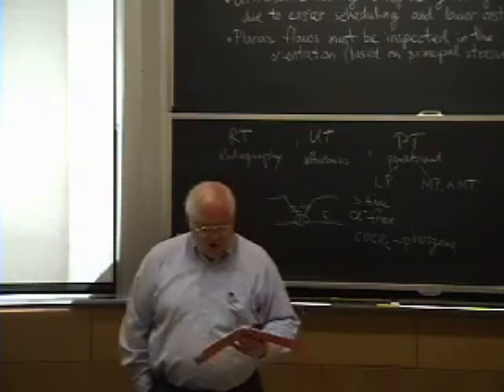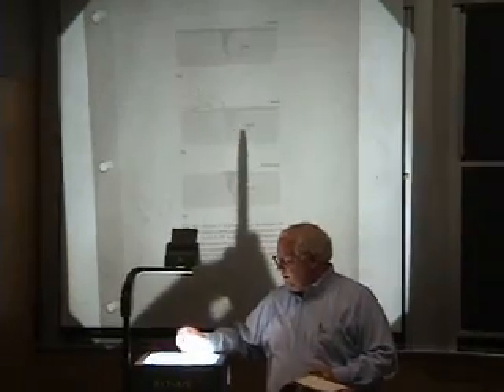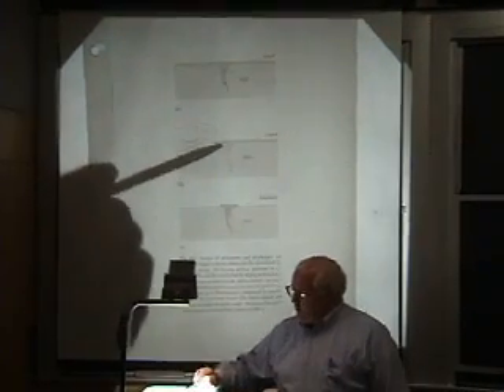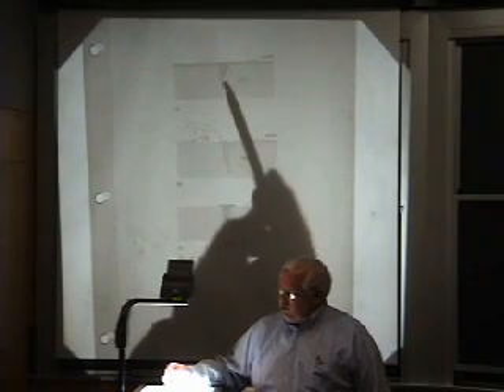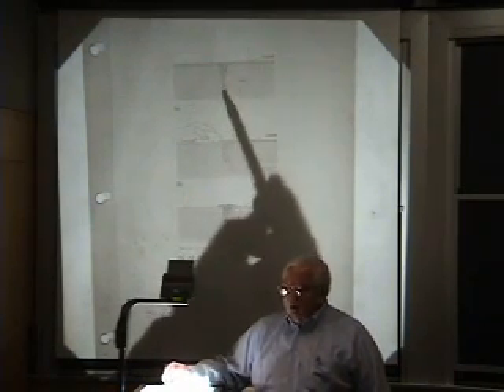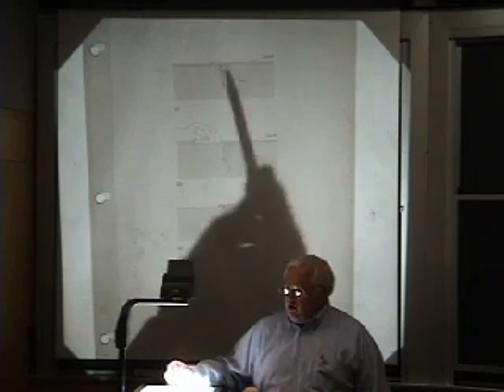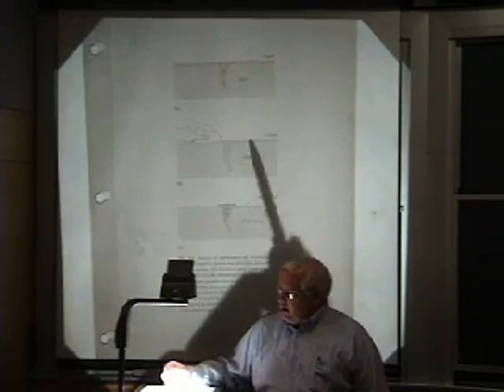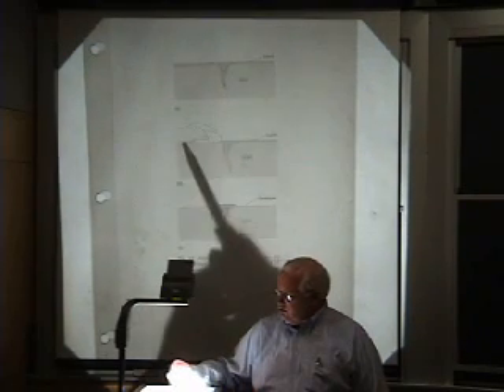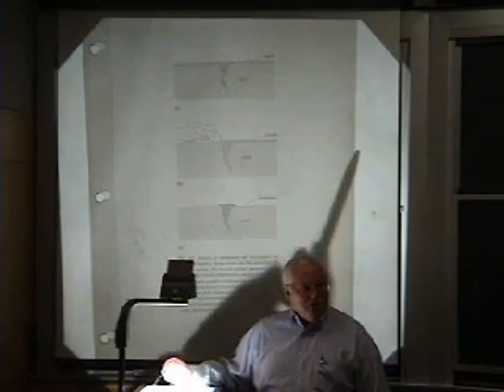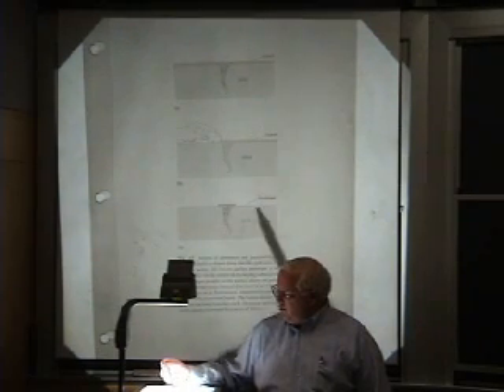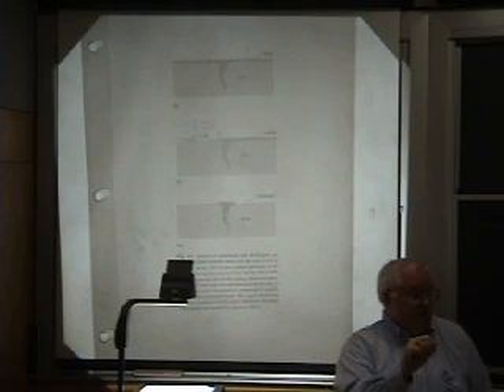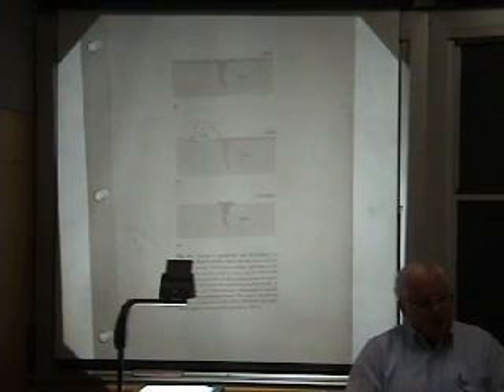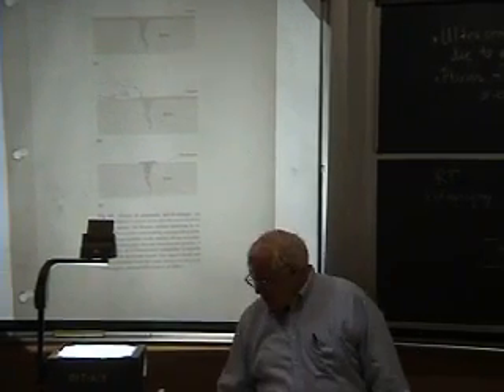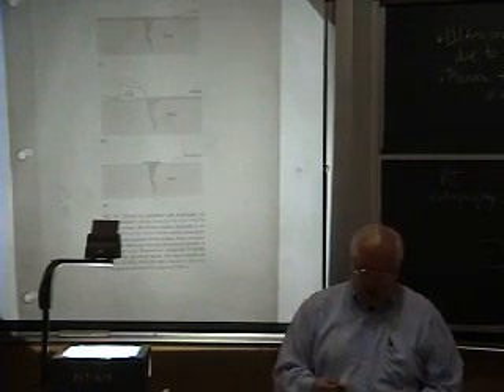And the liquid penetrant basically goes into the crack. If you have one of these simple little tests, you basically spray on a cleaner to clean the surface, then you spray on a typically red dye, and you let it sit for about 15 minutes to give it time to soak in. Then you take the cleaner and you clean off the dye. So this is the liquid dye that goes into the crack. You can wipe it off, but then you typically will spray clean some of that. And then you put a developer on, and the developer is just kind of a white powder that you spray on. Again, it's in one of these aerosol cans. You spray it on, and it will soak up some of the dye, so you'll get essentially a red dye on a white background for that type of liquid penetrant.